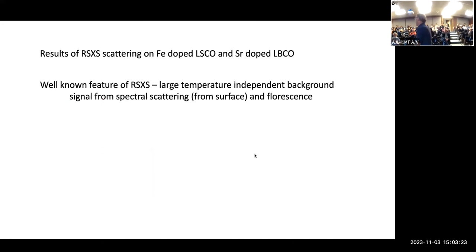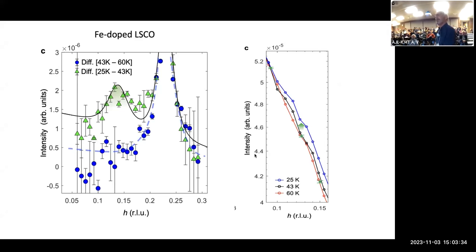So the way people always interpret this data is to subtract a high temperature signal, which one assumes to be the background, from the low temperature signal. And so that's what I'm doing here. So this is the difference between 43 Kelvin, just below the PDW ordering temperature, but far from uniform superconductivity, where you see a very strong 2Q peak, but nothing at 1Q. And then this is going to the lower temperature, where this 1Q peak appears very clearly in the difference spectrum.